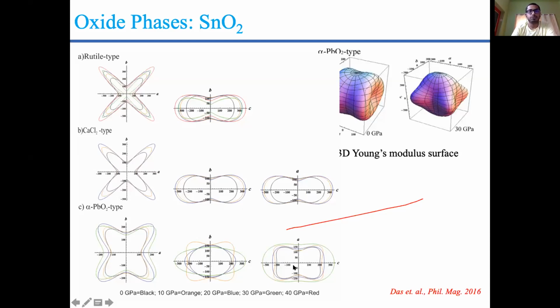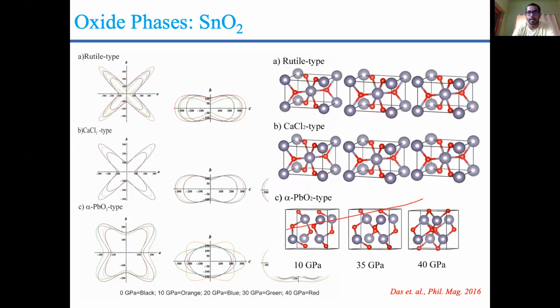So from these findings, we can conclude the crystal structure of the alpha PbO2 phase becomes more planar and compact at high pressure, which you can see from this, which is missing in the other two phases.